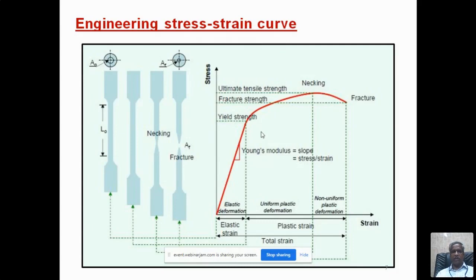We have one machine, a tensometer, which is a tabletop machine. In that, you can test even 25 mm, 1-inch length specimens. So based on the machine capability, you can fix the length of the specimen. And once the total length is fixed, the gauge length should be fixed based on either the diameter of the specimen, if it is a cylindrical specimen, or the thickness of the specimen, if it is a sheet specimen or plate specimen. Once the gauge length is fixed, it should be marked on the specimen, and then you hold the specimen firmly, rigidly in the machine by clamping, and then you select the loading rate.